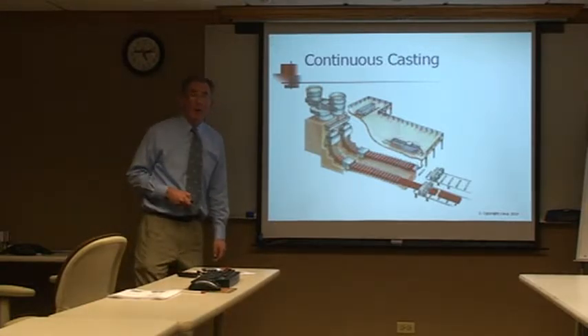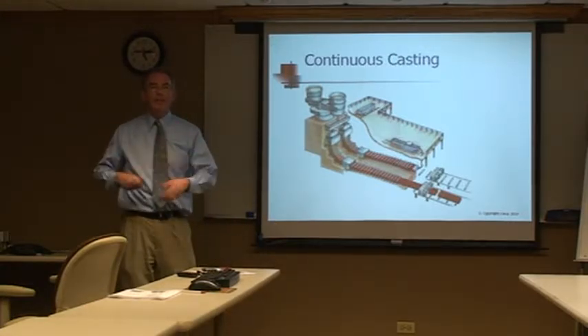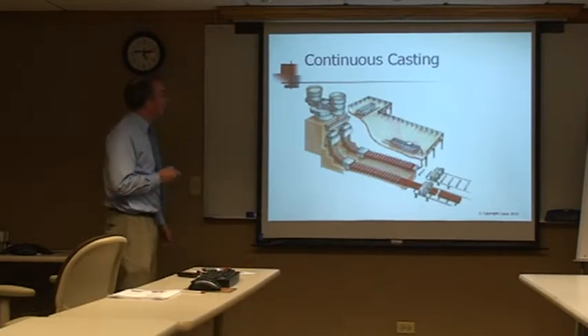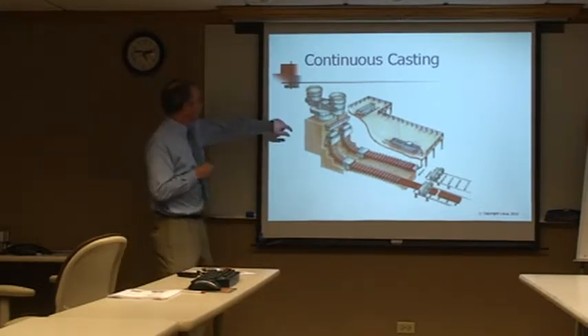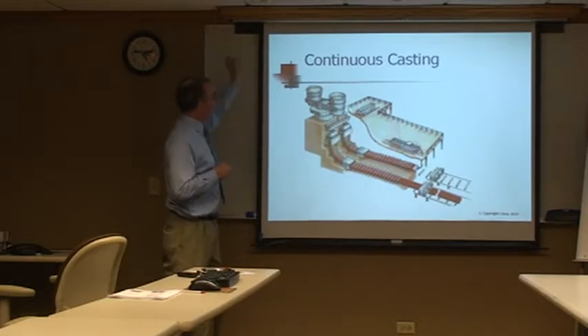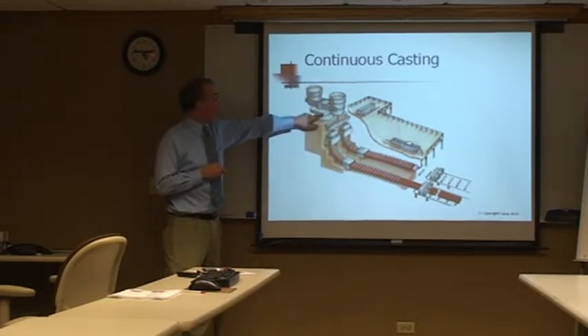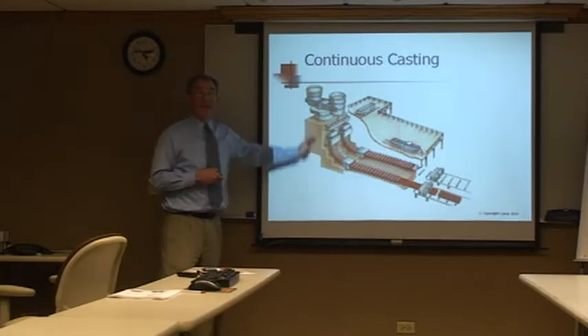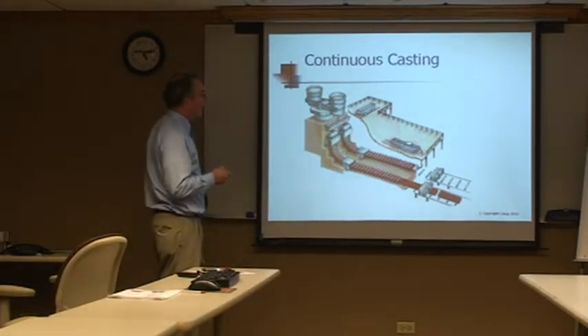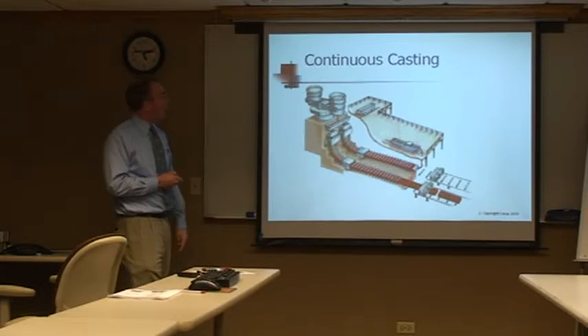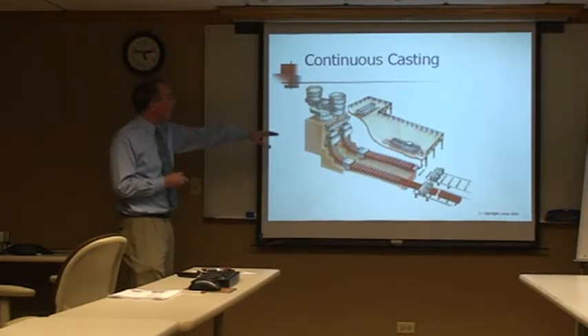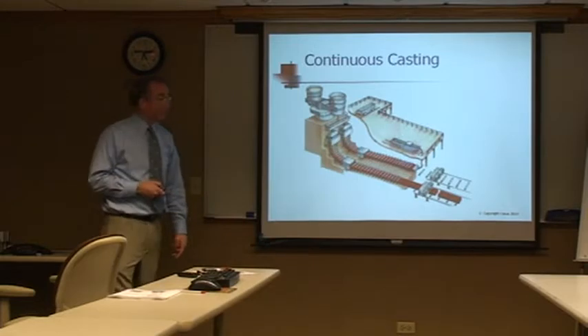The thing that makes this so advantageous is it's continuous. So for very high volume, same grade, same size, heat after heat after heat, this is the way to go. Because you fill this tundish up, and look at this turret up here. Once this ladle's empty, this turret spins 180 degrees, and bam, this ladle is here and it's pouring. Then the empty ladle is removed, and a new ladle comes in and is staged, waiting for this ladle to finish. So it's a continuous operation, because this tundish is a little bit of a buffer. It always has liquid steel, filling these molds.